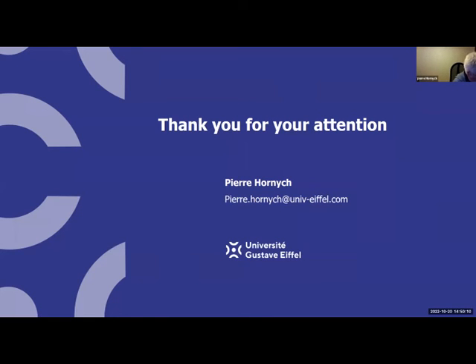And is that temperature you predicted on the surface or at the height? The temperature that I showed is the maximum temperature in the asphalt layer. And in fact, it's close to the coil. It's just above the coil. The temperature on the surface is a little lower. Thank you.